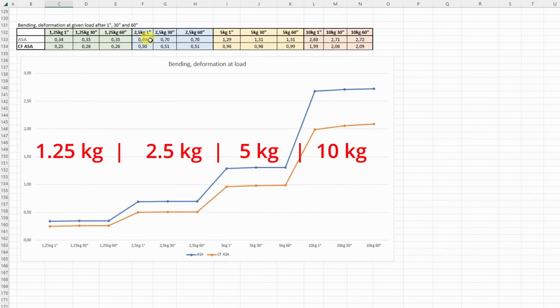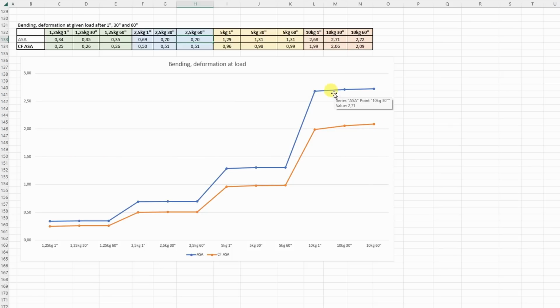So let's say this is the deformation when I place 2.5 kilograms: the initial deformation, after 30 seconds and after 60 seconds. And as you can see, this is very good. I mean, if we had a nylon, then we have some kind of angle because it continuously deforms. But let's see this one on 10 kilograms. Yes, smaller values are better, so carbon fiber has less deformation, but look at this, it didn't stop creeping even after 1 minute, so it has this additional deformation, while the regular ASA had a bigger deformation, but then it stopped deforming, even at 10 kilograms. So carbon fiber is good, but only on the smaller loads.